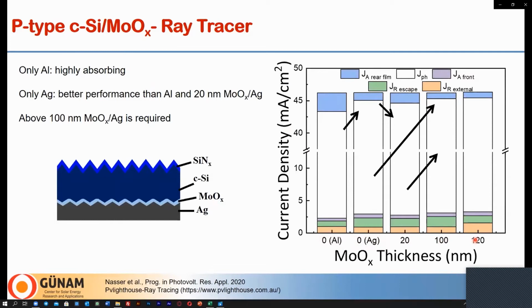So in brief, we found that a rather thick molybdenum oxide of at least 100 nanometer is required to increase photogenerated current density, which is also coupled with a reduction in the amount of current that is being lost at the back surface.